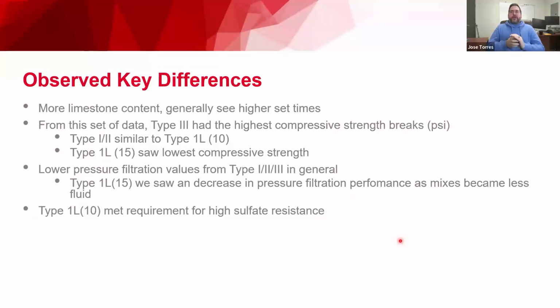And really, in terms of the key differences we observed: the more limestone content that you have in your mix, generally we see higher set times. Of course, you can control that with accelerators. I think there's some good data there.